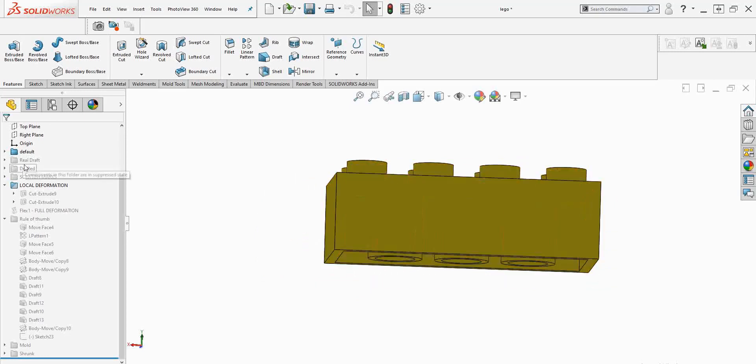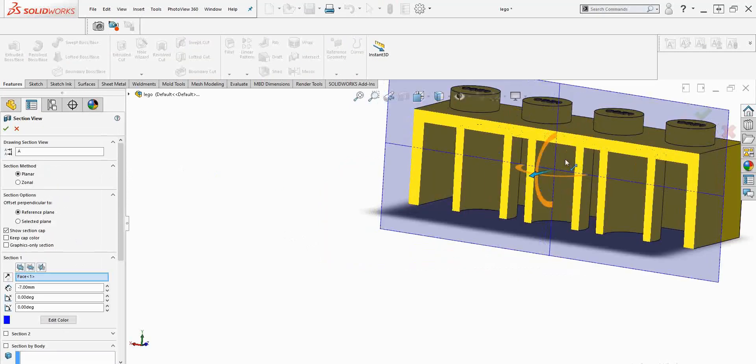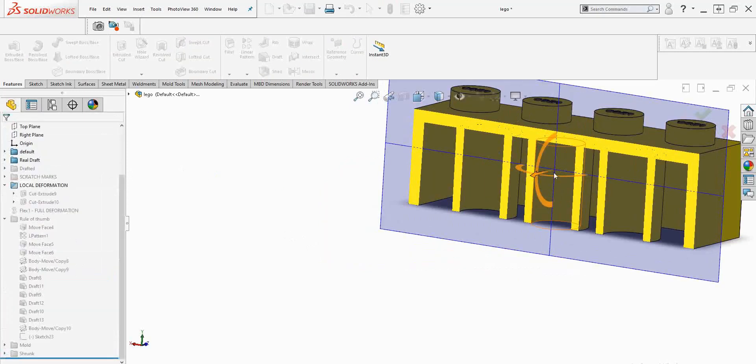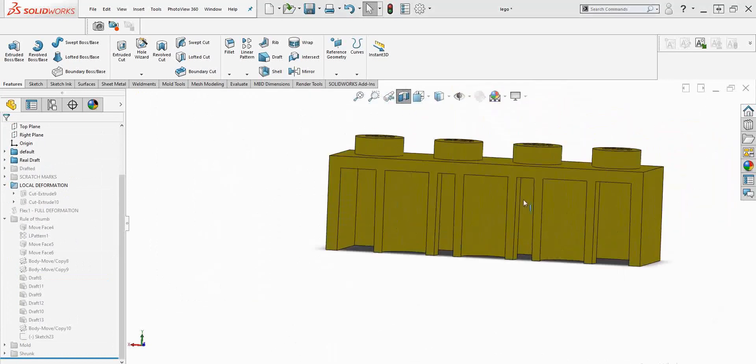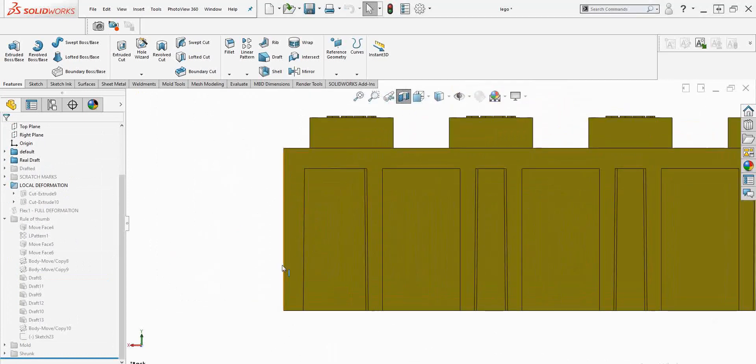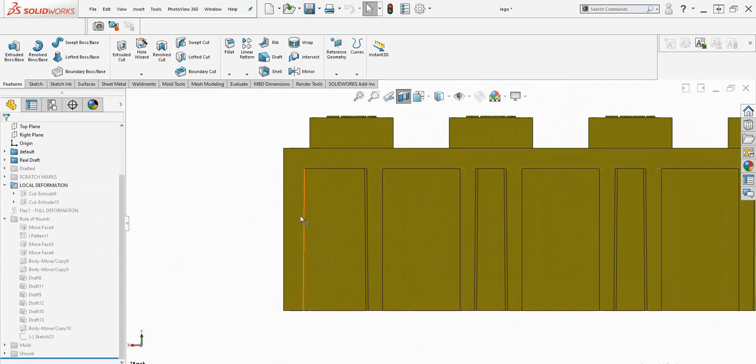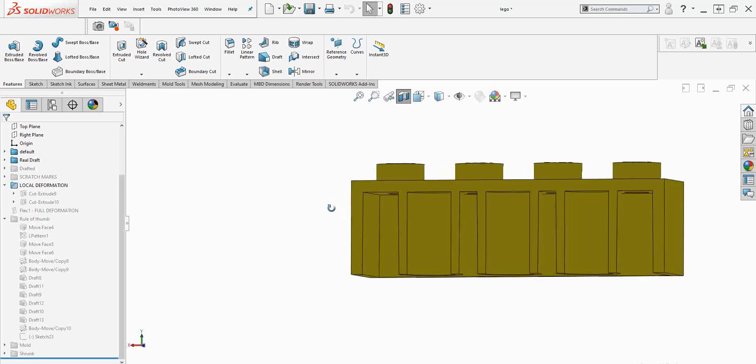So if we look at the Lego block in its real drafted form, draft angle on the inside is 0.5 degrees and the draft angle on the outside is 0 degrees. There is no draft angle. You literally can't even see it. It's so slight. So that's probably why you can't actually see draft angles a lot in injection model products that you own. Because the outside walls are not drafted. And if they are drafted, it's so slight you can't even see it anyway. And the inside walls are always drafted. But why is it that the outside walls can be zero degree draft and the inside can't?